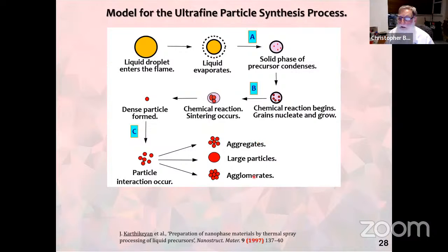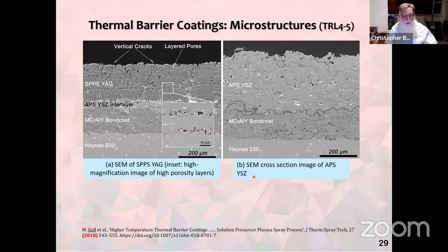So liquid thermal spray has now advanced even further. In the more recent past, here are some examples. On the far right, you see a conventional atmospheric plasma sprayed yttria-stabilized zirconia coating, a conventional coating on a conventional bond coat on a superalloy. And now what we have is the same substrate, the same bond coat. We have an interlayer of a conventional coating, and now we have the solution precursor plasma sprayed yttrium aluminum garnet coating.